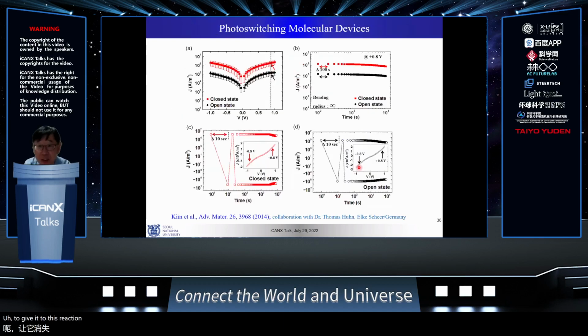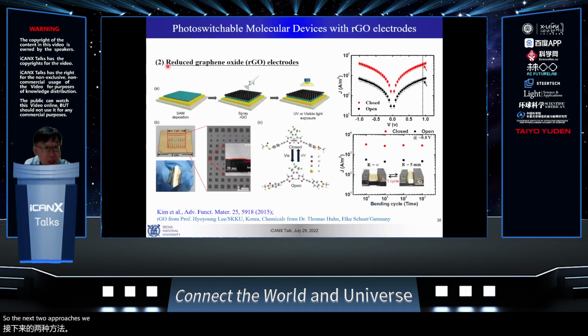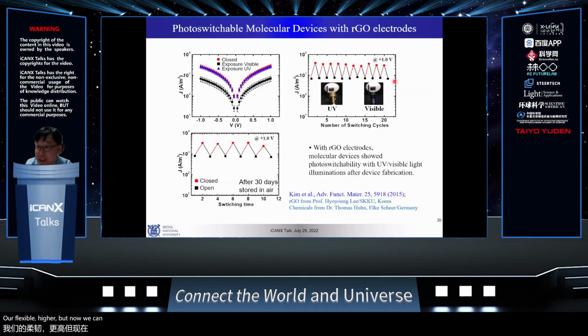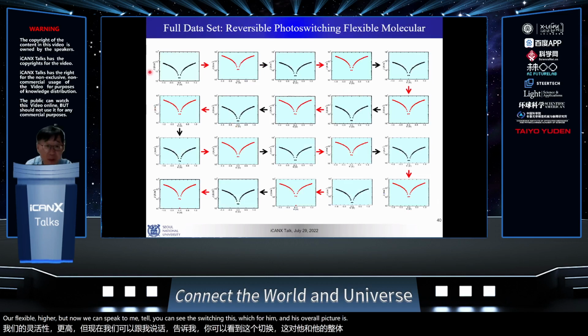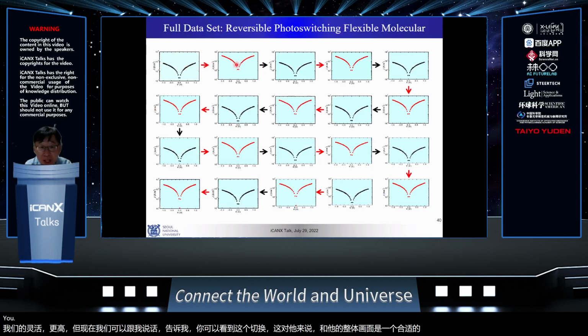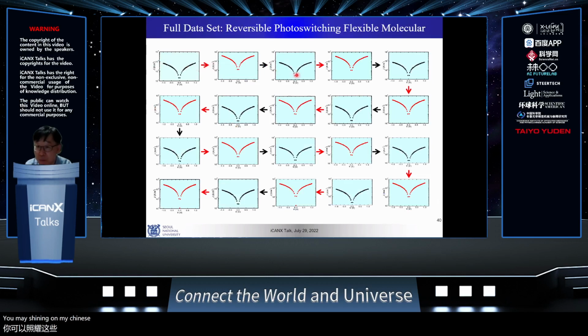Okay. So the next approach was we changed to reduced graphene oxide spin coating on top of the molecule instead of the conductive polymer. So this is still the same. It's on, off by shining UV, by shining visible, on and off configuration, flexible, high yield. But now we can switch this. Okay, you can see the switching, this is switchable. And this overall picture is switchable: off, UV shining on, visible shining off, UV shining on, and repeating, and so on and so on.